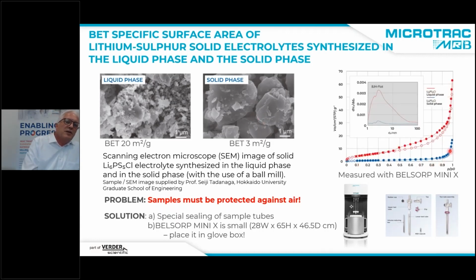The isotherms of the ball milled lithium sulfur electrolyte show a low uptake of gases, and that also results in the BET surface area of 3 square meter per gram, while the electrolyte we got from the liquid phase got a much higher surface area of about 20 square meters per gram. We also see that in that case we have to deal with some kind of pores in this lithium sulfur solid electrolyte from the liquid phase.